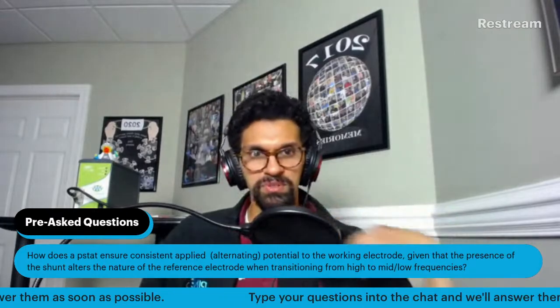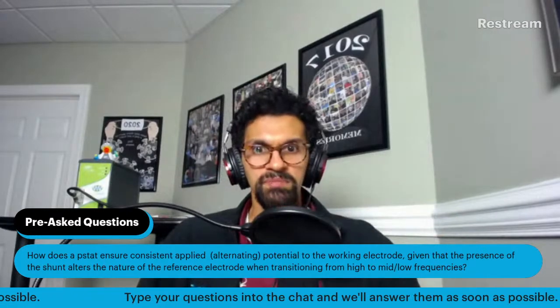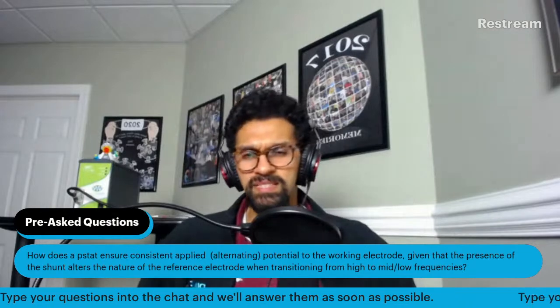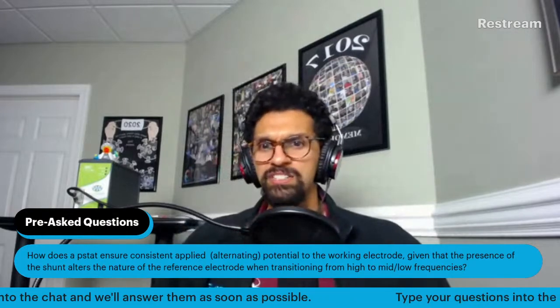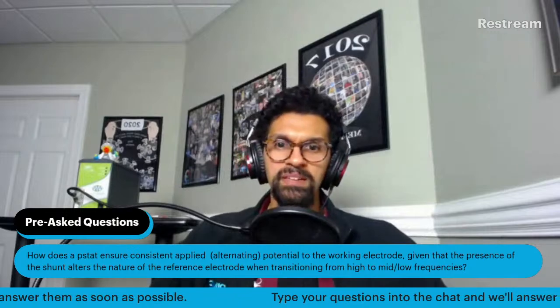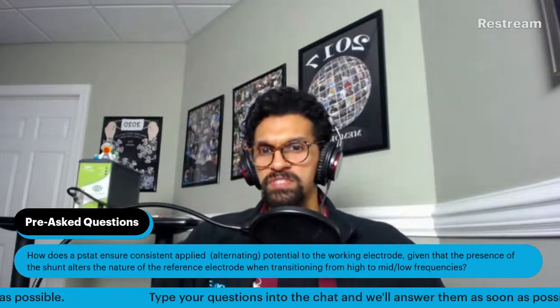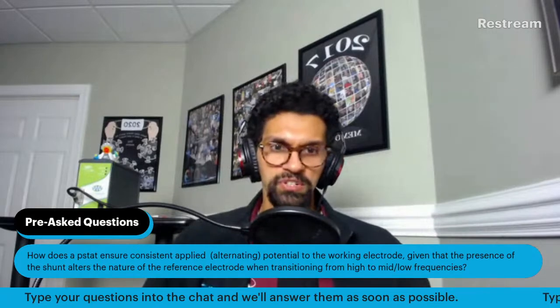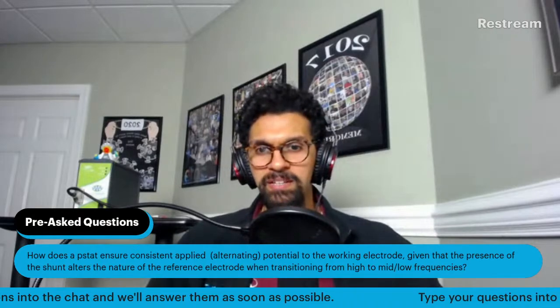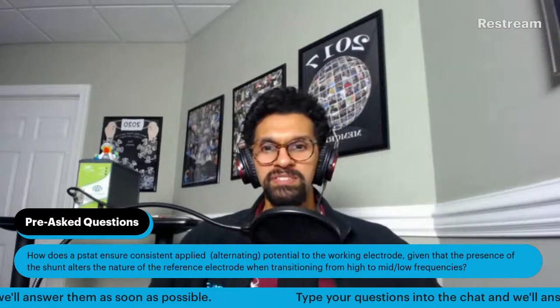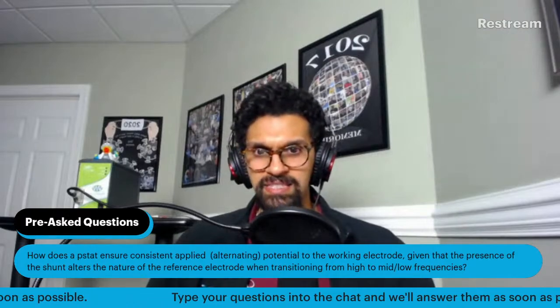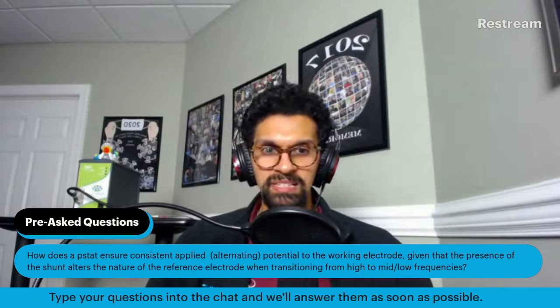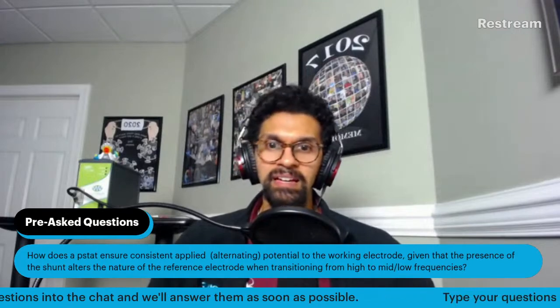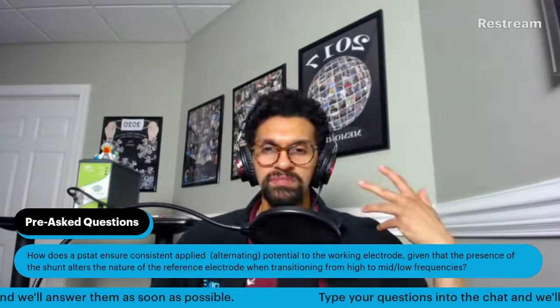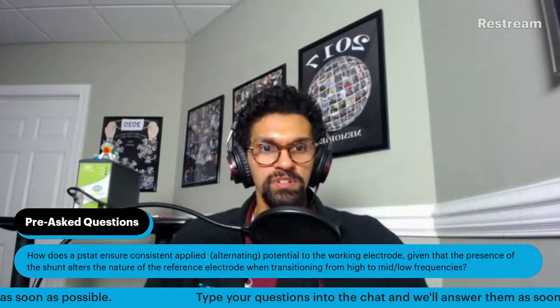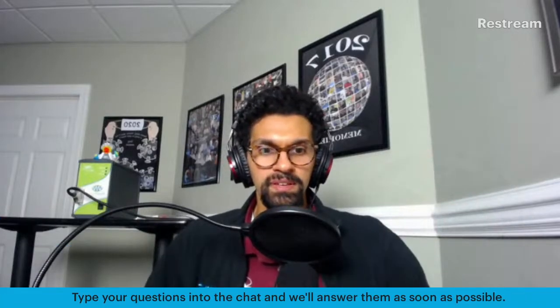So his question, for those of you who are unfamiliar with this part of EIS, is that in some cases when you're doing electrochemical impedance spectroscopy, because you are using a reference electrode such as silver chloride or saturated calomel, you end up running into these high frequency artifacts in your Nyquist plot. You get this kind of bad data, and to solve this, we use what's called a reference electrode shunt.